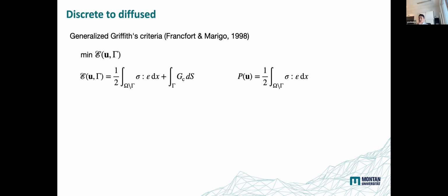So what are we doing? What equations are we solving? With the generalized Griffith criteria, we can write the problem as follows. We want to minimize this energy. The energy is a sum of the mechanical energy, which is the stress times the strain, and then the second term, the surface energy. So this is the discrete problem. We want to minimize this total energy with respect to displacement and crack set gamma.